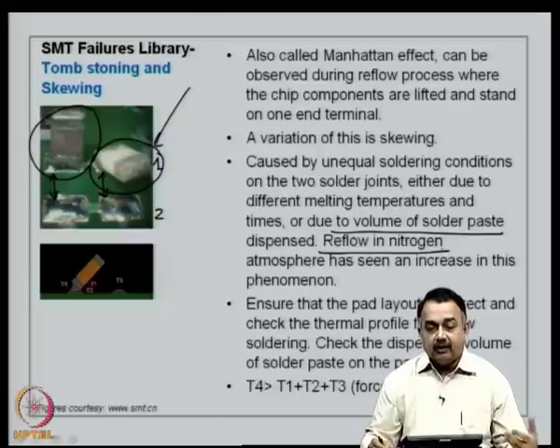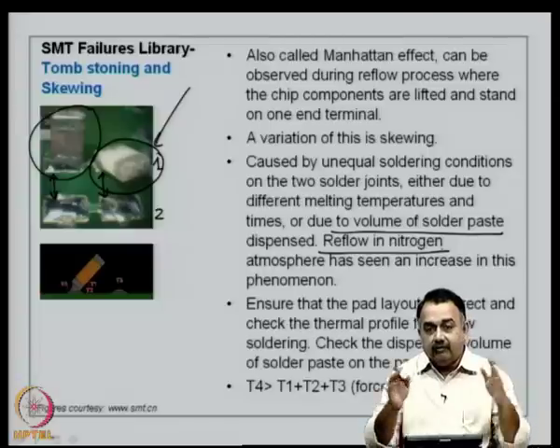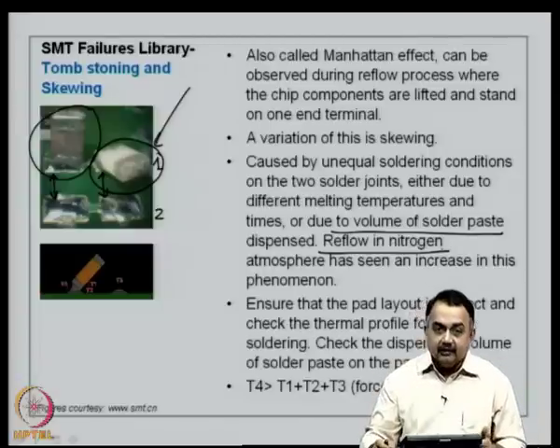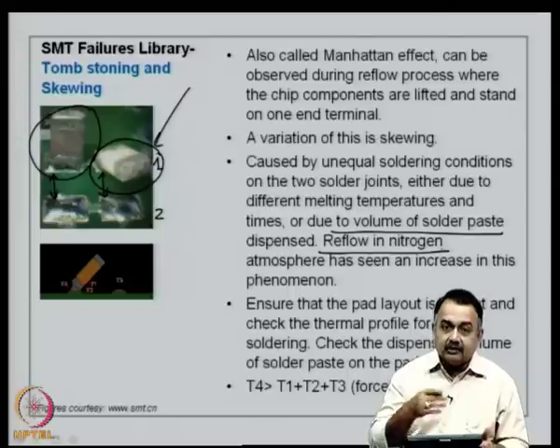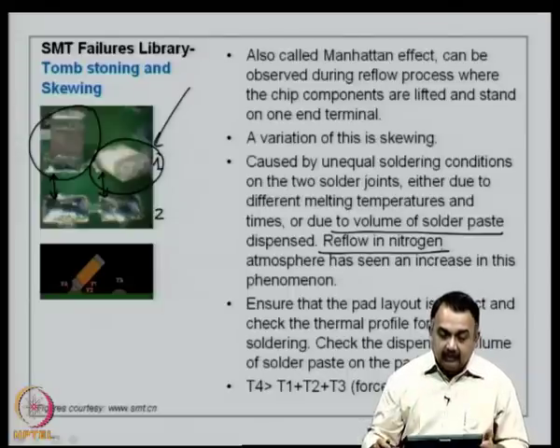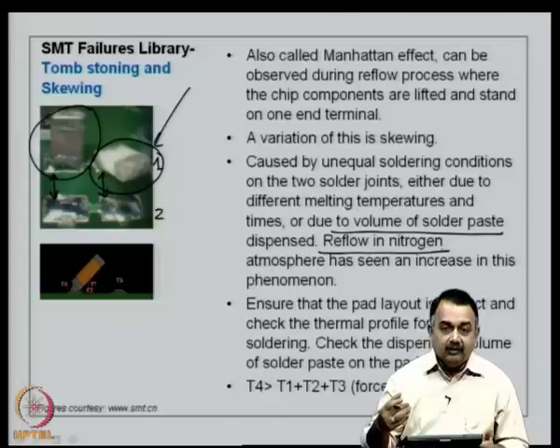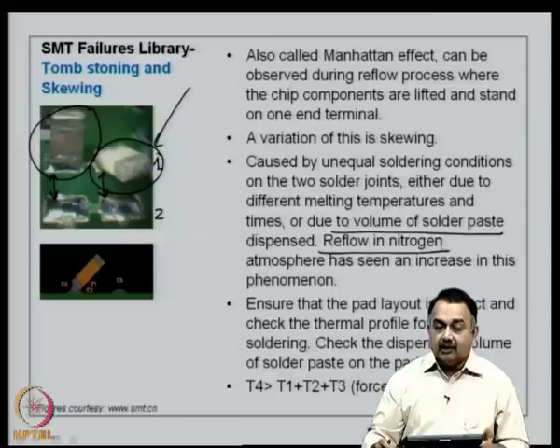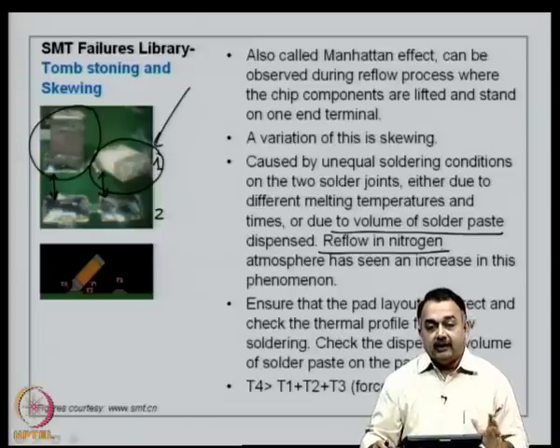Normally, reflow soldering is done in air. That means your reflow oven has air, convection based, and there will be air circulation. And typically, the solder paste gets activated well in air. Now, there are certain solder paste materials which are recommended to be used in nitrogen, basically because of the composition of the solvent and other components of the solder paste. But then the thermal profile is slightly different for a reflow process in nitrogen atmosphere and that which is done in air.